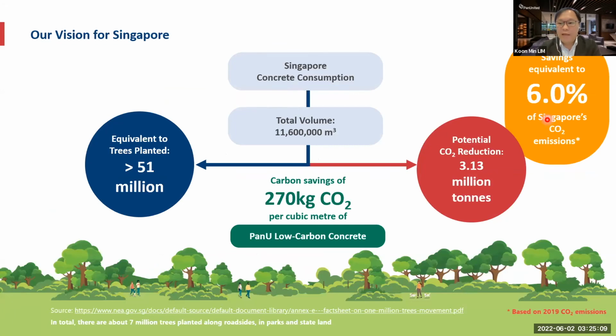And what we really want to envision in Singapore is, if we use low carbon concrete, reducing 270 kg CO2 per cubic meter of concrete, right, we are able to reduce close to 3.13 million tons. And this 11.6 million cubic meters is the Singapore concrete production last year. So the effect is quite significant, and that 3.13 million, we are talking about close to 6% of Singapore's emissions.